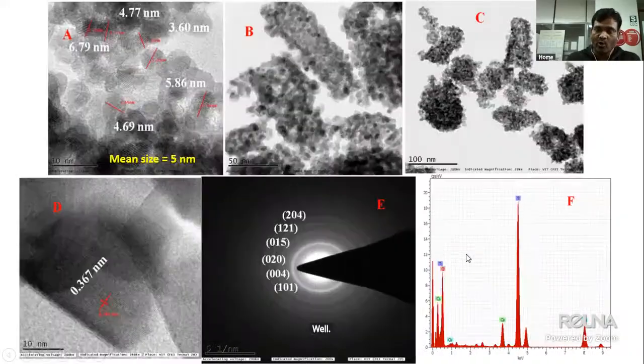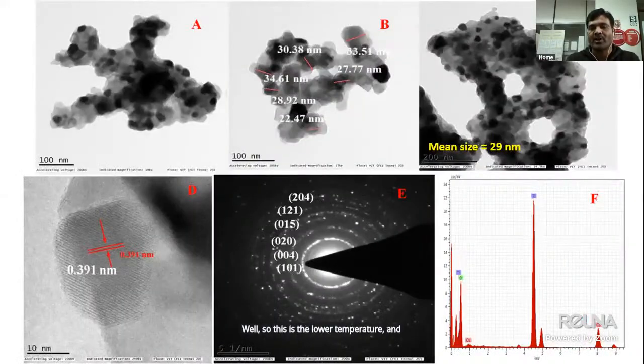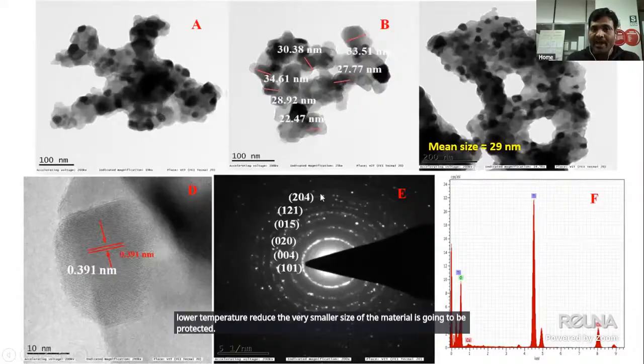Well, so this is the lower temperature and this is the higher temperature. The lower temperature shows a very small size of the material being prepared. While looking at the higher temperature, 800 degrees Celsius, the titanium dioxide material shows a larger size of the material. Okay, so the mean size is 29 nanometers.